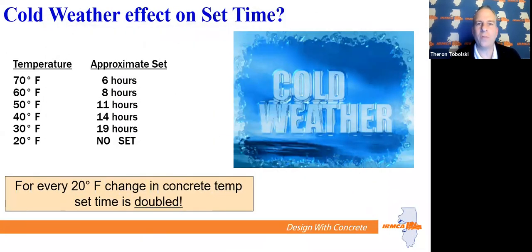How does cold weather affect concrete? We kind of see here, if we had a 70-degree concrete, this concrete mix would approximately set in 6 hours. And every degree in concrete temperature that the concrete decreases, the set time increases. So when we go to 60, we go to 8 hours. When you have 50 degrees, we go to 11 hours. 20 degrees, we're not going to get any set.